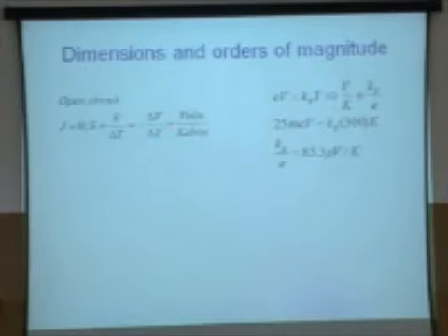And it comes about from a fundamental unit. You can think of eV as energy, kBT as energy. We know kBT is 25 millivolts at 300 Kelvin. And from there, you get kB over e is 25 millivolts over 300 Kelvin, which is about 83 microvolts per Kelvin. So this is a fundamental unit, and we measure the thermopower in units of that. The question is how large I can make it: is it 5 times or 1 time? So that's the number, or dimension and number.